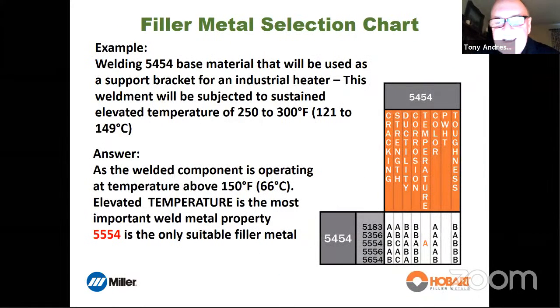Here's an example, and it's a temperature example, which is a good one. We've got some 5454 base material, and I know this is a 3% mag maximum base alloy, which is typically designed to be used at elevated temperature. It's going to be used as a support bracket in an industrial heater, and it's going to be subjected to 250 degrees Fahrenheit for prolonged periods.